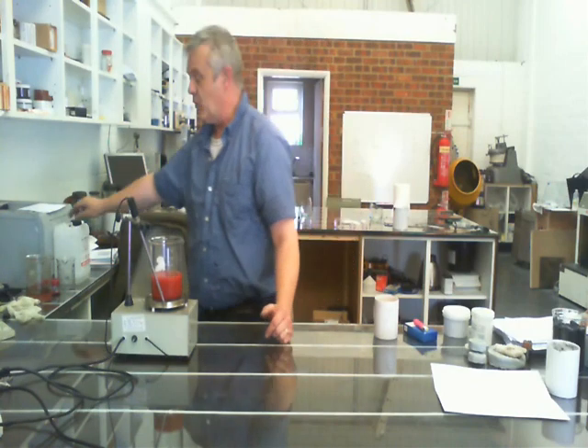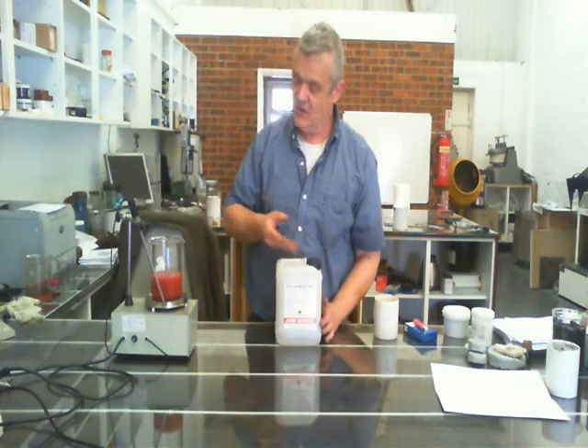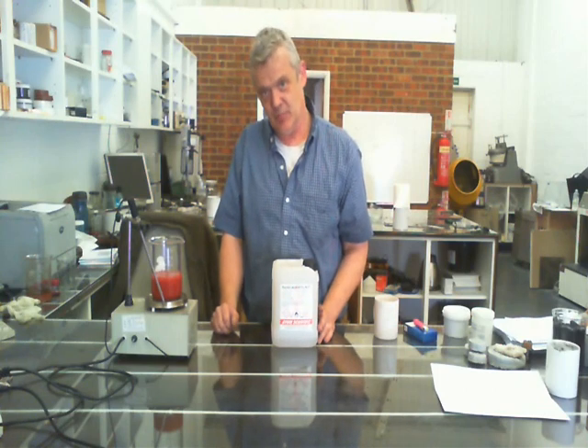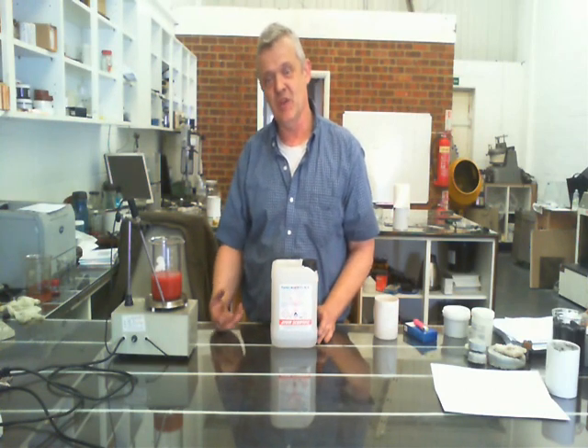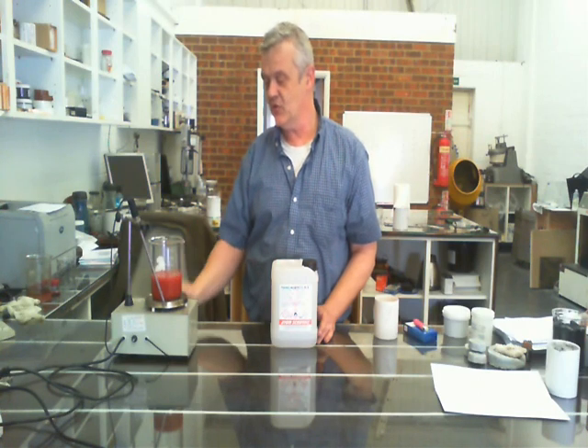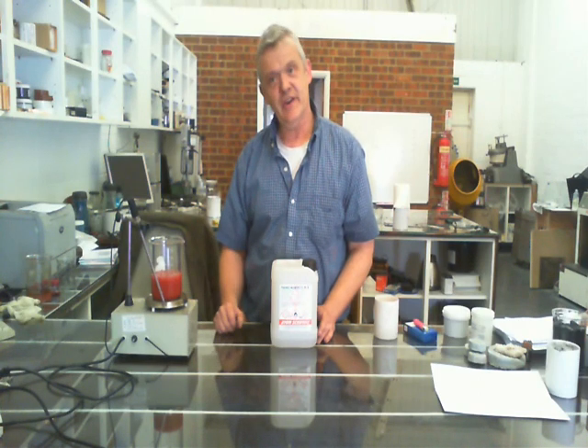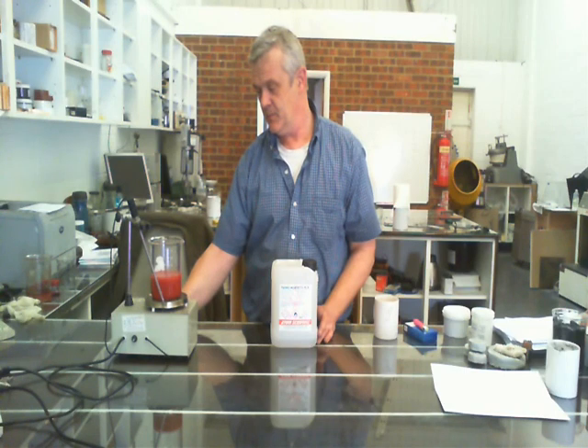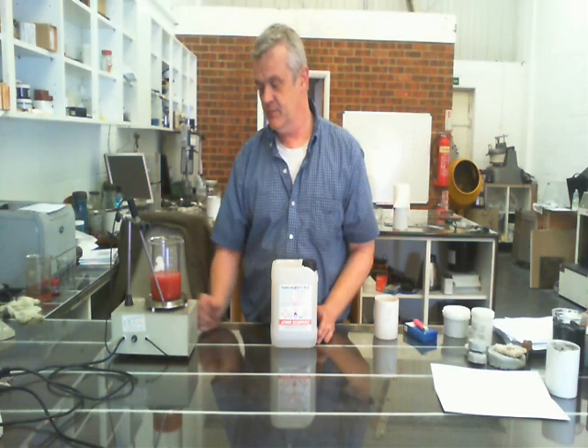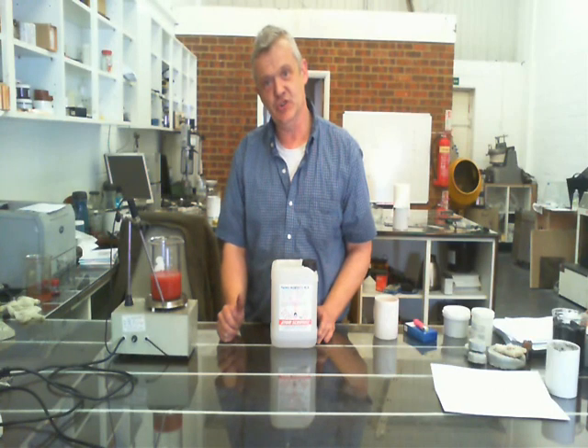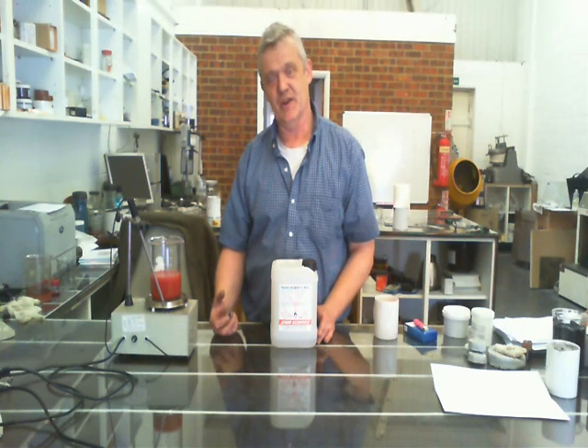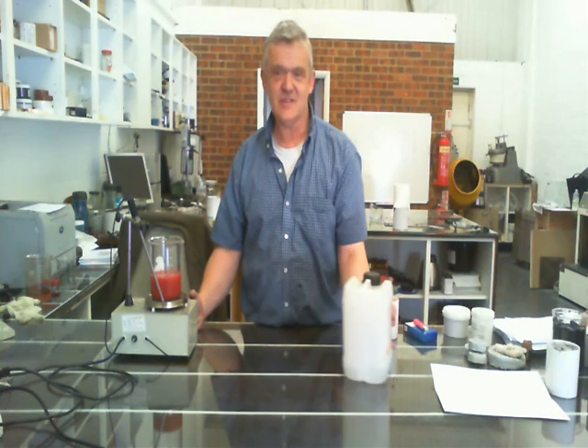Now, normally you can't make copper nanoparticles out of an insoluble salt like this, but what I'm going to do is reduce that using formic acid. Formic acid will turn the copper oxide first into copper formate and then reduce it down to copper metal. And that process means that we can control it through concentration to change the morphology and size of our copper nanoparticles. Now, as I said, this is actually a new synthesis. I haven't seen this anywhere.